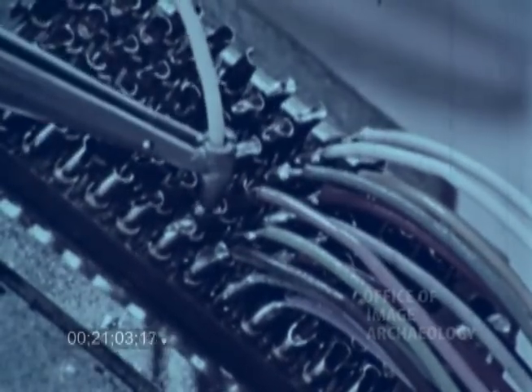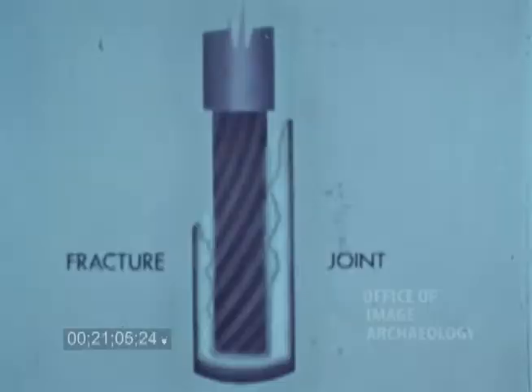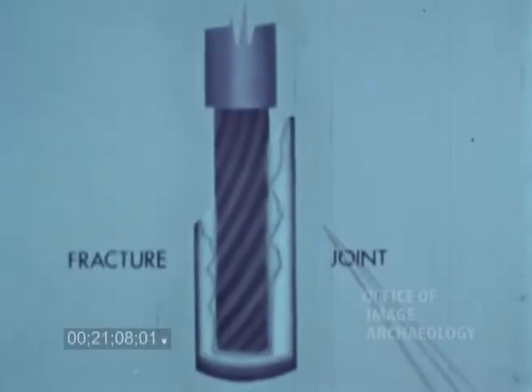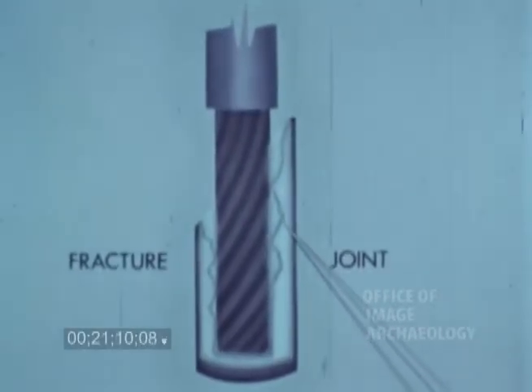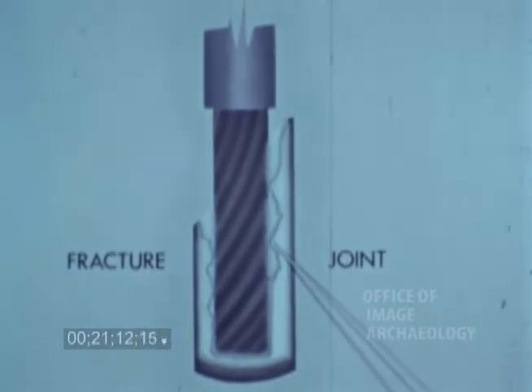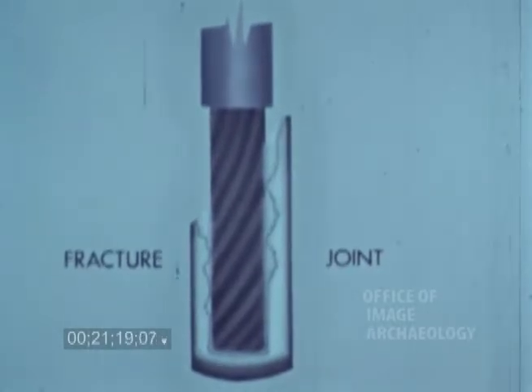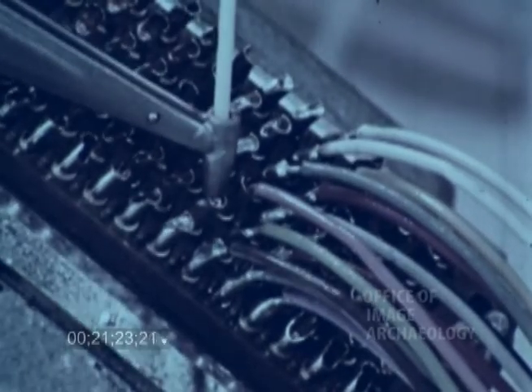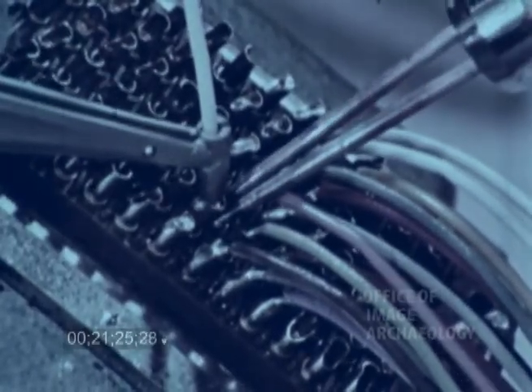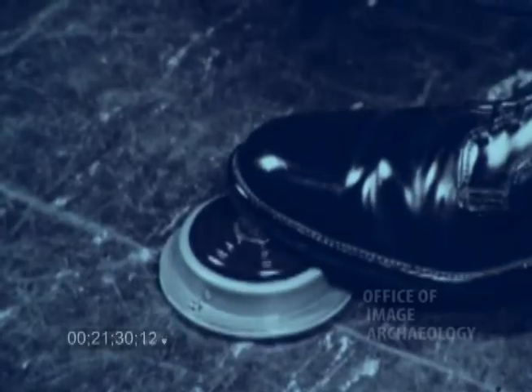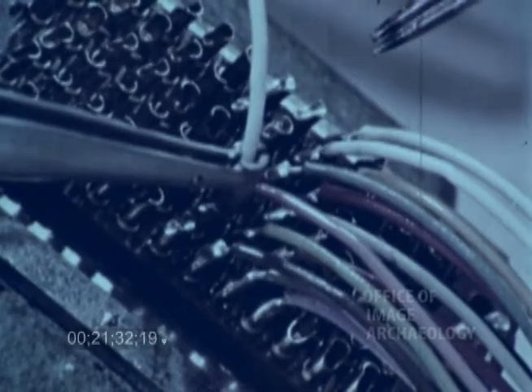Be careful, you fractured that connection. By removing the wicking tool before the solder had completely solidified, a fractured joint will result. It's easy to see that this connection cannot perform as a solid piece of metal. In most cases, a fractured connection can be repaired by reheating the cup. Hold the wicking tool steady until the solder has solidified.